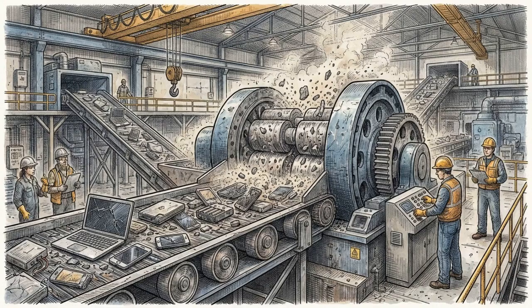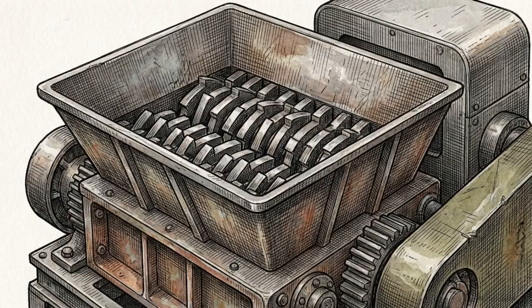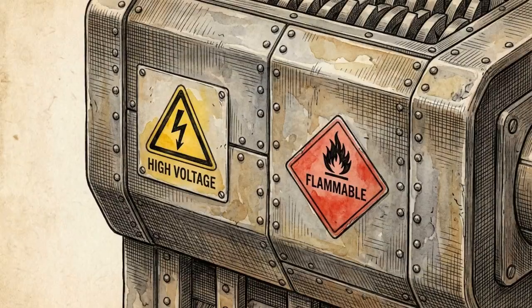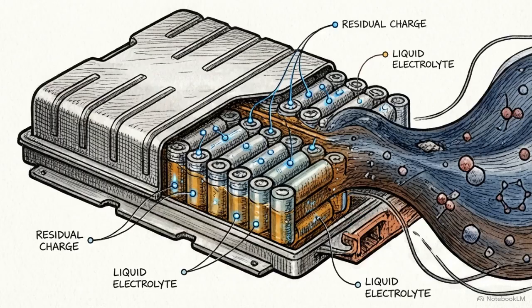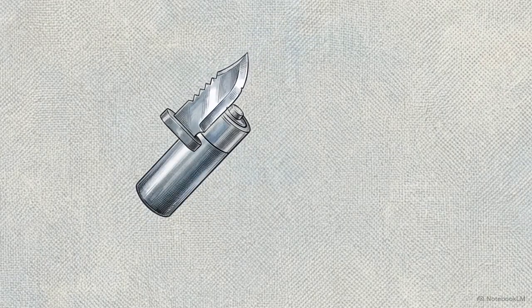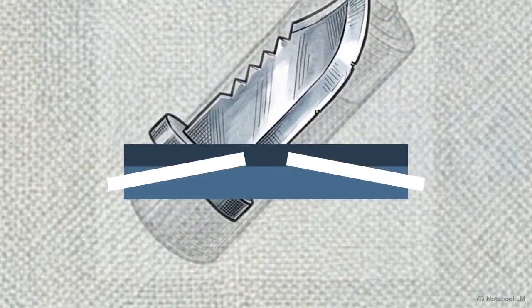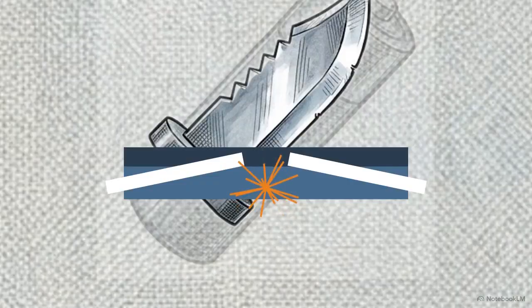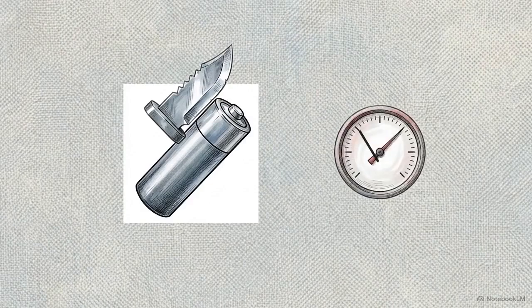The recycling process begins with mechanical comminution, which involves physically shredding the battery to access the active materials inside. This stage presents a severe industrial danger. A spent battery often retains residual electrical energy and houses highly flammable organic liquid electrolytes. If a steel blade breaches the cell in ambient air, the separator is crushed. This forces the positive and negative layers together, causing an immediate short circuit. This triggers thermal runaway, an exothermic chain reaction where internal temperatures rapidly exceed 1000 degrees Celsius.